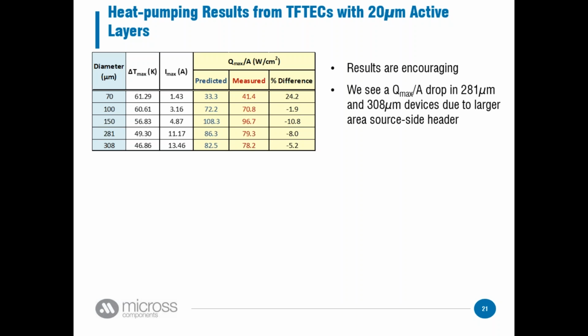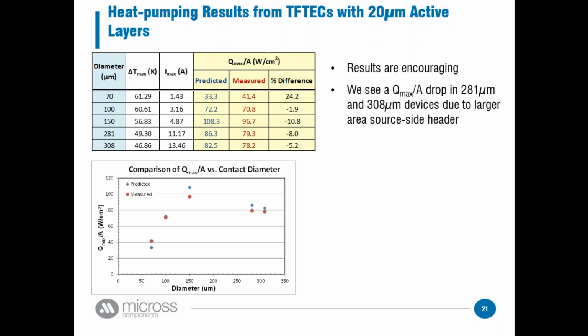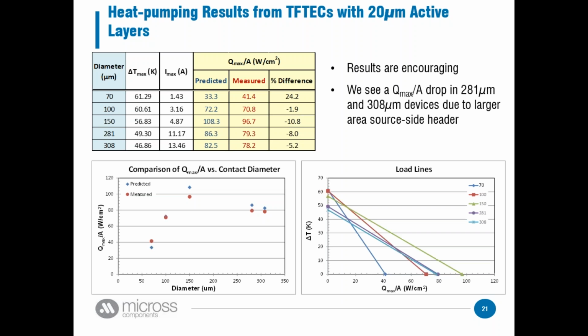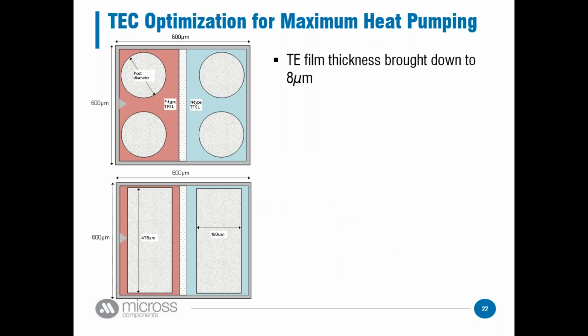We had some problems with these modules here because they had a larger area, and so we lost, even though we had a lot of heat pumping, a lot of heat coming through them, the pumping per area wasn't as good. And so you could see, we're getting numbers which are around 100 watts per centimeter squared. Like, wow, that's 10 times better than what the bulk guys do. But, we grow 20 micron material. Can we drop down? Can we grow lower? Can we grow maybe 8 micron material?